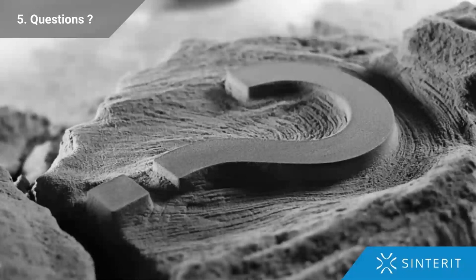Let's say you have some sort of steps. Those steps will generate smaller gaps than you have originally. So if you are printing at a specific angle, you will need to make even higher value gaps. So not smaller, but higher value gaps. And if you will be printing a joint, as I said before, perpendicular to the print bed, then the gap can be smaller. So that's, I think, the answer to the question.